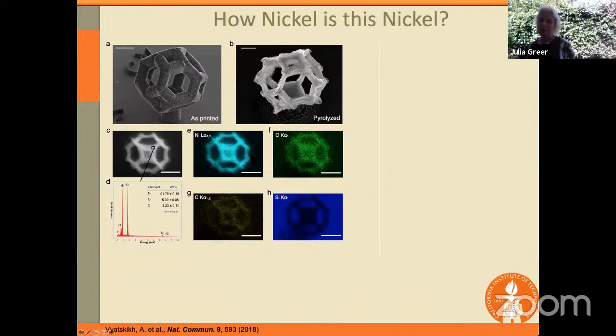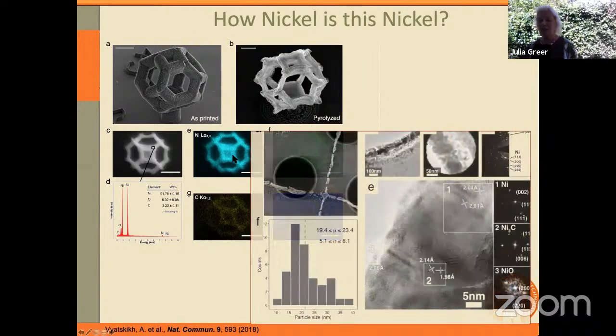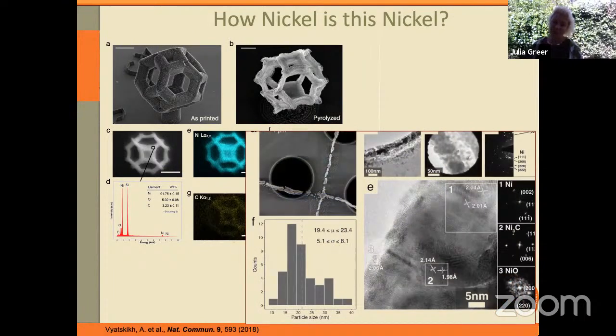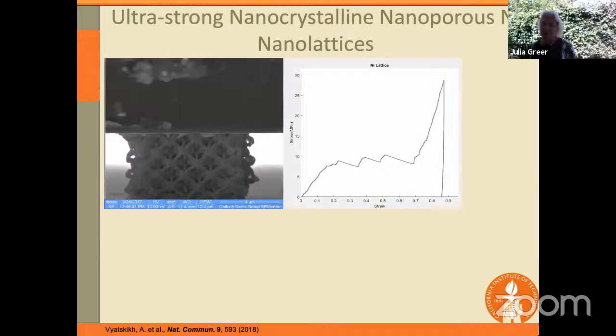So we did quite a bit of chemical characterization. You can see that mostly it is indeed nickel. We did some microstructural characterization using the TEM, transmission electron microscope. Now you see the grain size here is on the order of 20 nanometers. So it's very nanocrystalline, and it's mostly nickel with some nickel carbide and just a little bit of nickel oxide. So now let's look at the mechanical behavior of this material.